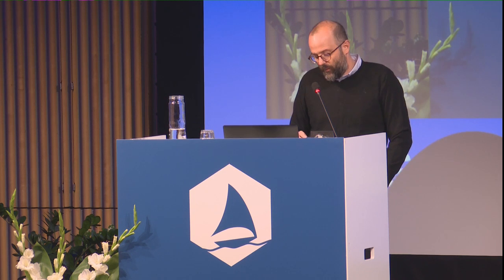The origin of this, I don't really have time to go into today, but it has to do with the way that these lattices actually relax once you place them together. So the graphene is not a rigid system. It relaxes into a strain configuration when we place it on boron nitride. And understanding how that strain develops as a function of pressure allows us to reproduce this, at least in one theoretical model. But the basic punchline I want to emphasize is that this gap can basically be made to diverge as a function of pressure that we apply. In this case, we get a factor of two.